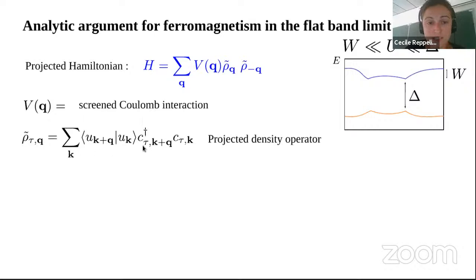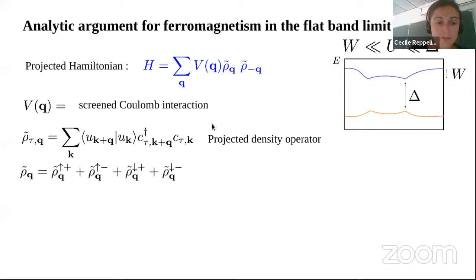And this is something we see through this form factor, which appears here as the overlap between two wave functions. So I'm showing here the projected density operator for just one valley and one spin. This is what the tau here means. And in this form, this is where the topology and the Berry curvature and all these sort of things are hiding when you do the projection. The overall projected density operator corresponds to the sum of all spin and valleys.